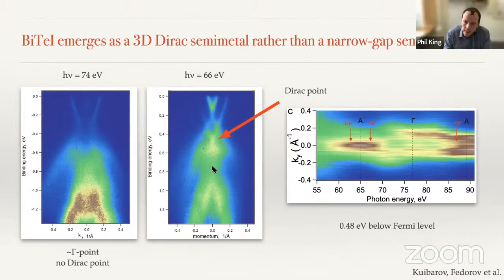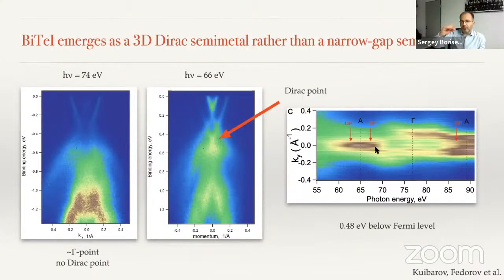So if you take this KZ map that you show on the right at the Fermi level, do you see all the bands dispersing there as a function of KZ, or do you also have 2D states? We have a dispersion of that. We showed that we see the dispersion of the size of the Fermi surface by about 10%. It's in line with this quasi 2D Fermi surface which we have, because the 3D Fermi surface which we advocate is actually quasi 2D. So this is a different interpretation. We think this quasi two-dimensionality, which has always been seen, is actually evidence, like the first de Haas-van Alphen study showed that this Fermi surface is quasi 2D, and that's why these states are bulk rather than surface. Great, thanks very much.